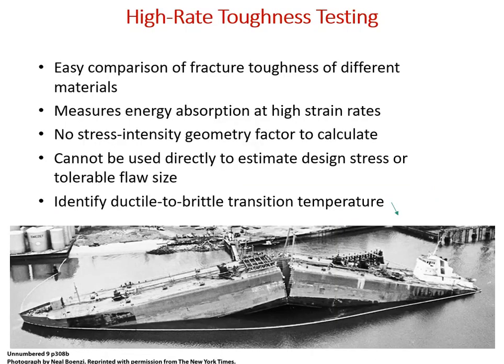Okay, and that is it for this lecture. It's definitely been a long one. Just to wrap up, the most important coverage we've had is the concept of brittle failure, low energy absorption materials, the inability to ductilely deform or to plastically deform being basically the biggest reason you would encounter brittle failure, and then the fracture mechanics that led up to the ability to define a K1C, a critical fracture toughness that was material specific, that could nonetheless only be used with an understanding of the pre-existing flaw size, its relationship to applied design stress.